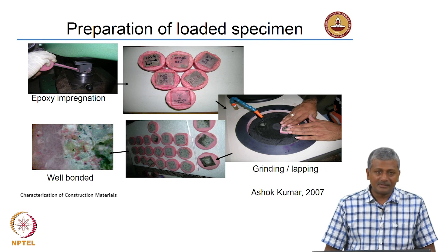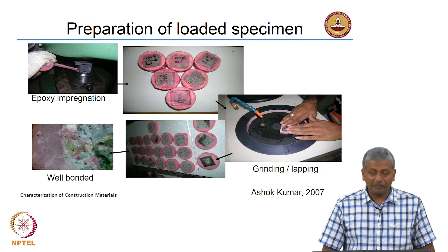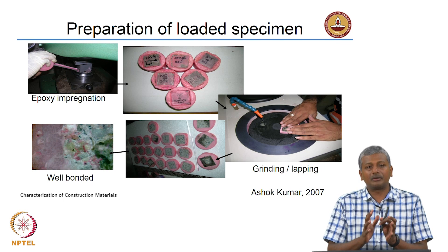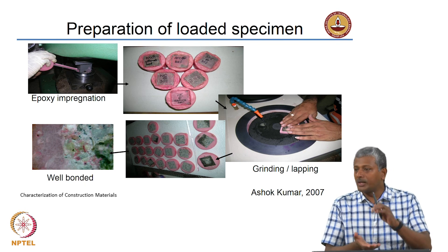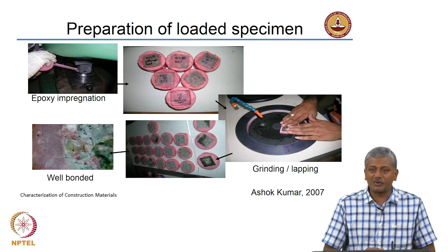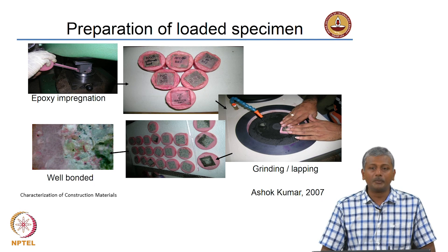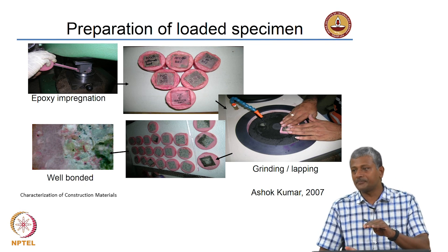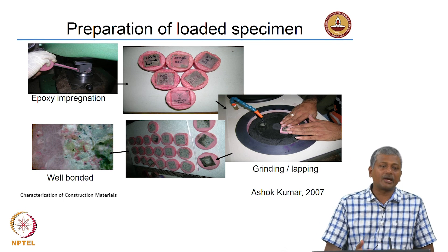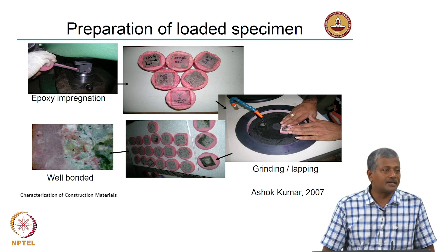In some cases, people have tried to investigate how the structure of a material behaves or changes when loading is applied. In this experiment we investigated concrete cubes loaded in uniaxial compression and wanted to preserve the cracked state of the cube at different stages of loading, to see how cracking progresses inside concrete with different stages of loading.